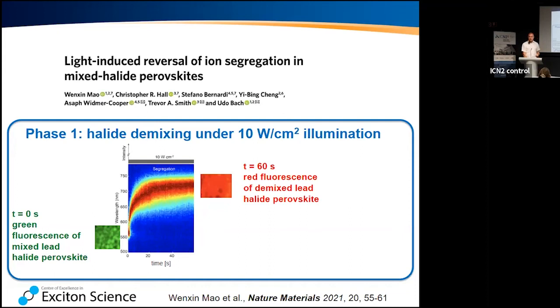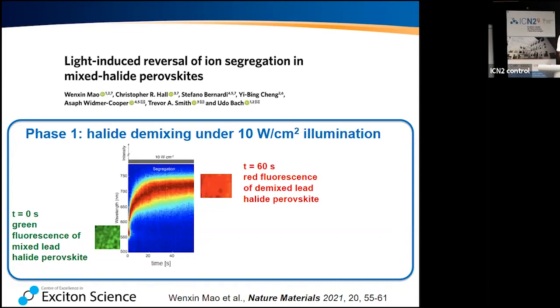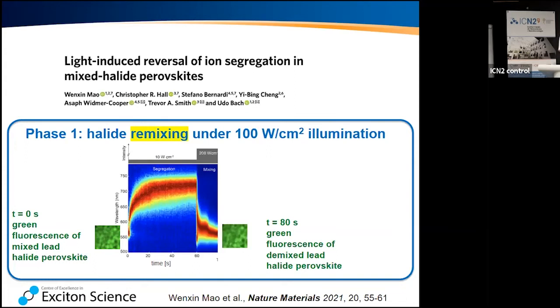Now, what will happen if we shine light on that that is, say, 100 or even more times more intense? What would be your guess? My guess would have been more of the same. But what's quite amazing is that if we now switch the light source and we shine high intensity light onto our crystal, what we see is actually it's reverted. Now, if we shine 200 watts per square centimeter light onto the same crystal, onto the same spot, our phase segregation, our halide demixing goes away and everything just mixes nicely again. So the same thing that caused halide segregation can also make it go back to fully mixed. So that's something that was quite intriguing and that we found quite interesting.